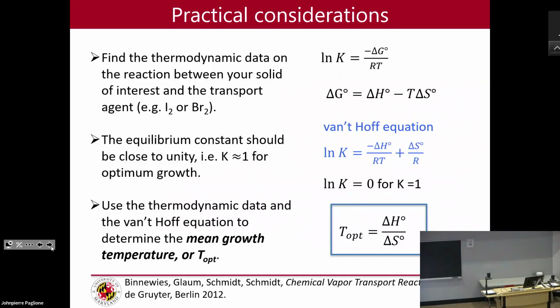So if you're doing transport between 2 different zones, first, you're going to ask yourself, is this an exothermic or an endothermic reaction? Because that's going to then mean, am I going to have the charge zone at the hottest temperature, or am I going to have the crystal growth zone at the hottest temperature, right? As I said, if it's exothermic, you're going to favor reactant at higher temperatures. So indeed, what you want for an exothermic reaction is you want the growth zone to be the hottest part of your two-zone furnace. And if it's an endothermic reaction, you want the other way around. You want the charge zone to be the hotter end of the tube.